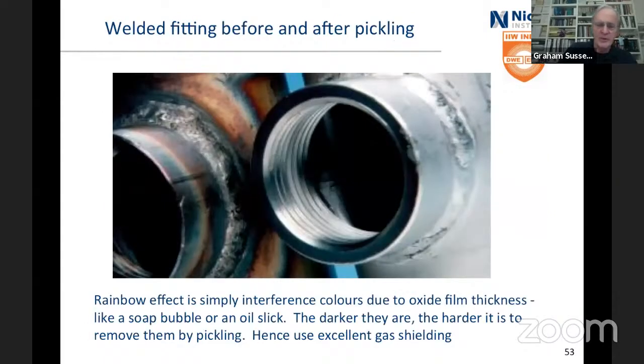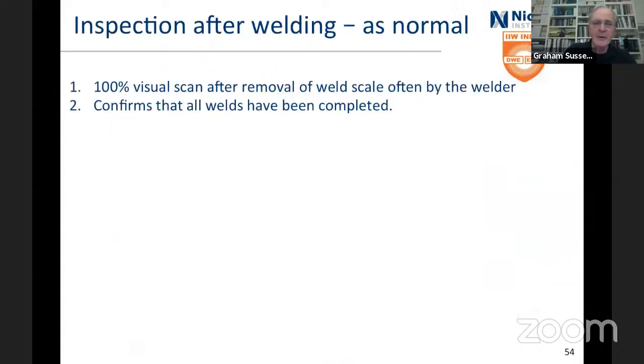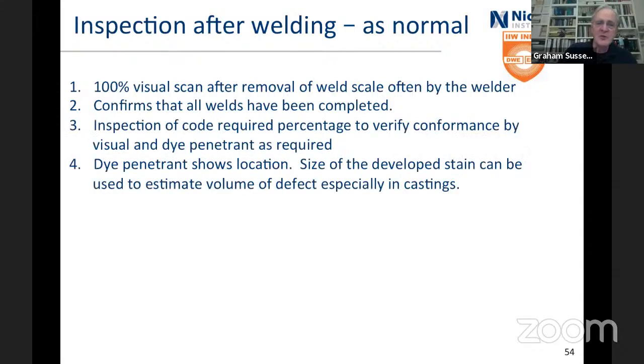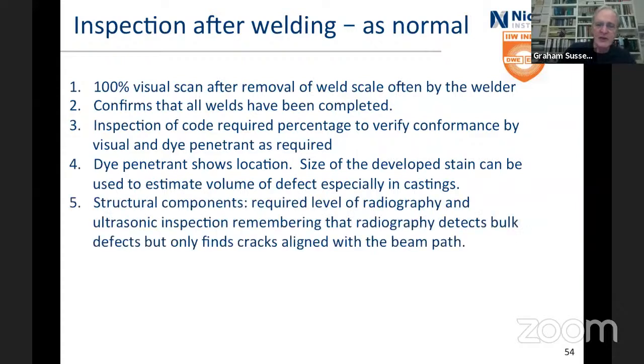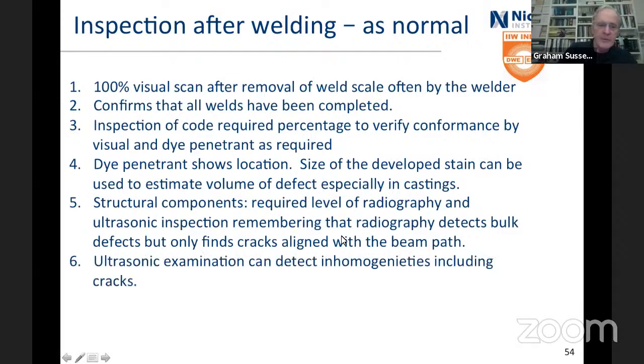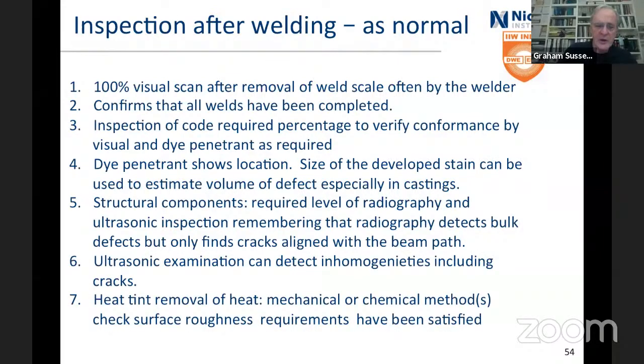Unlike this, which is a bit of a mess, because we've got lots and lots of heat tint on it, but okay, you pickle it and you get rid of it. If you wind up with that amount of heat tint on a duplex, then you're probably going to have phase problems as well, but okay, you can get rid of it by cleaning. And the inspection after welding, absolutely standard, the 100% visual scan, code work, dye penetrant for location of defects, structural components, you'll have radiography, all set by the code, and ultrasonics if you need to, and down to the bottom, heat tint removal, mechanical or chemical.